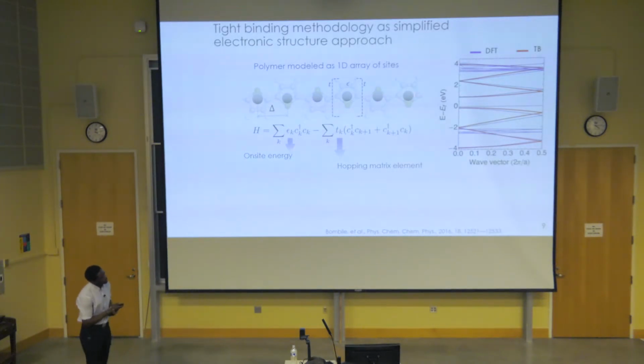Here on the right, you see that we have used density functional theory to determine the relevant parameters in the tight binding model by fitting the electronic structure computed using our tight binding model to DFT. And this is the band structure. It's simply a representation of the different electronic energy levels within the material, and particularly here is shown the fourfold valence band, and the valence band is simply the set of highest occupied electronic states, more relevant for the conduction of holes within the material. And this is a fourfold conduction band. Here again, conduction band is the lowest unoccupied electronic states, more relevant for the conduction of electrons.